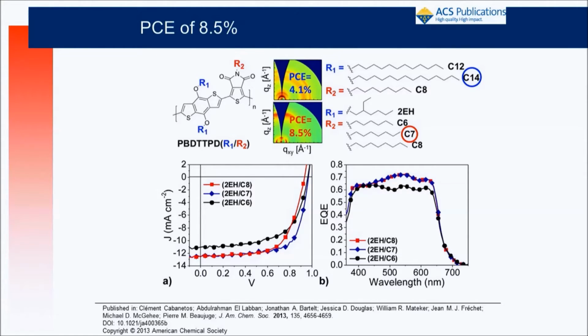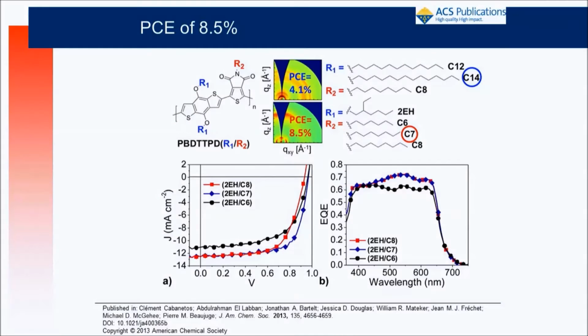So it's good news, bad news. The bad news is the fact that you have to make different side chains that will change the morphology, not the optical properties. The side chain won't modify the electronic band gap, the optical properties. It will just change the solubility, the processability, and also the final morphology when you blend it with fullerenes. And it's hard to predict. So you try, you make, you see, and you do your best. So instead of C8, ethylhexyl side chain, ethylhexyl side chain, C7, 8.5.